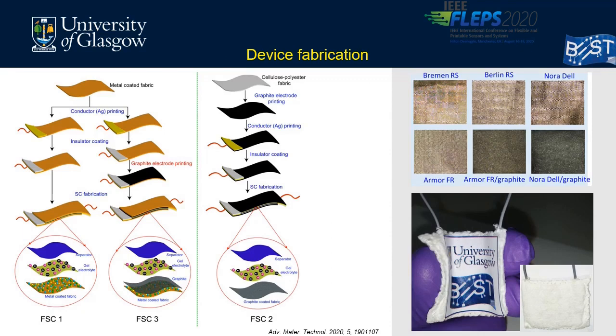This is the device fabrication steps we have adopted. We have fabricated 3 devices, namely FSC1, FSC2 and FSC3. In FSC1 and FSC3 we use the metal coated fabric as the current collector, but in FSC3 apart from the metal coated fabric we use an additional layer of graphite as an electrode to enhance the capacitance. But in the FSC2, in order to understand the role of metal coated fabric on the supercapacitor performance, we have used a non-metallized fabric, that is cellulose polyester, as the substrate. Then we have made a device out of this fabric by using graphite coating. So the graphite coating will act as the electrode material as well as the current collecting applications.